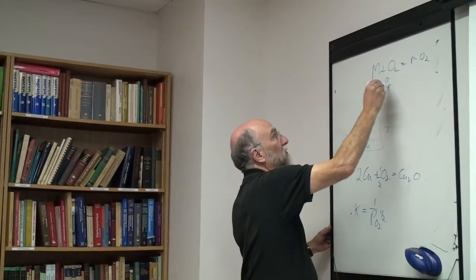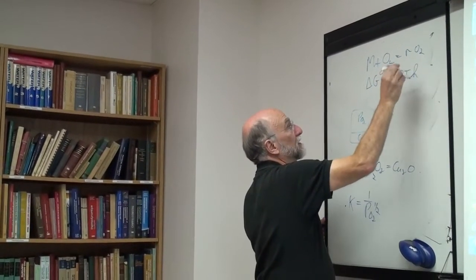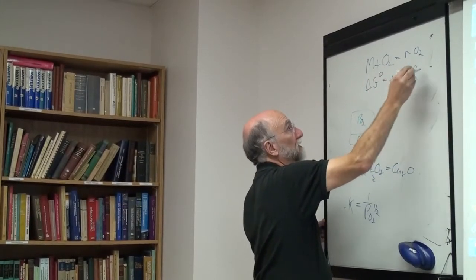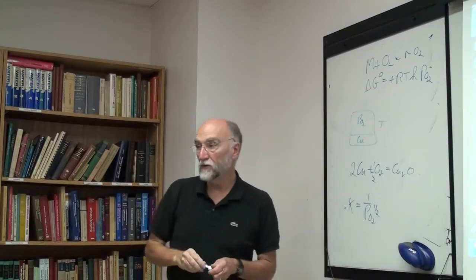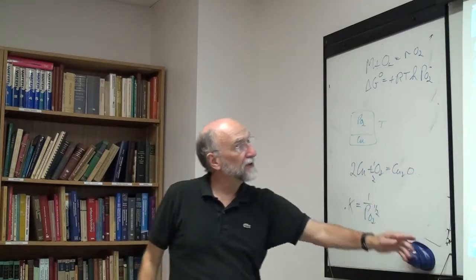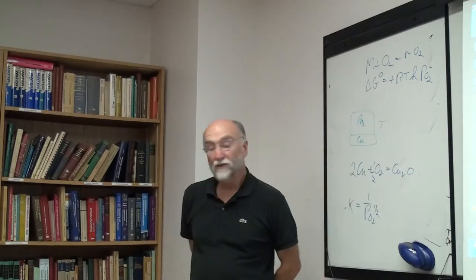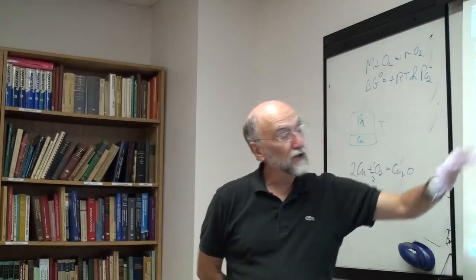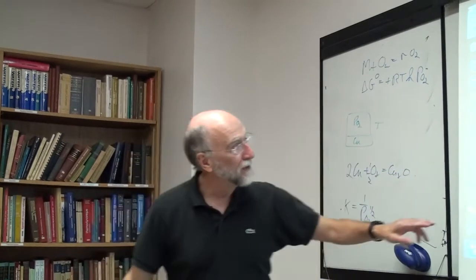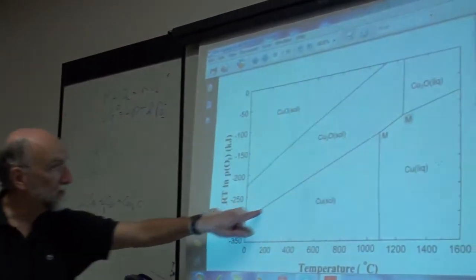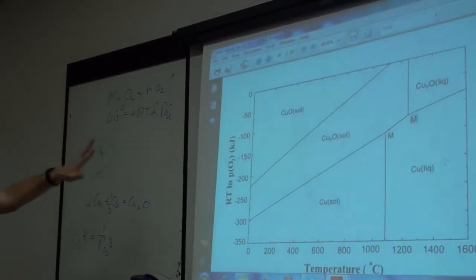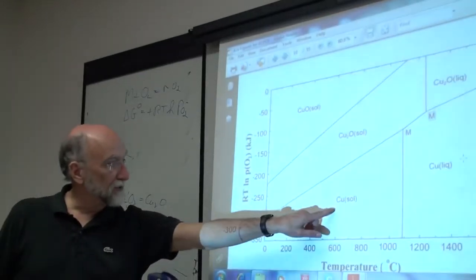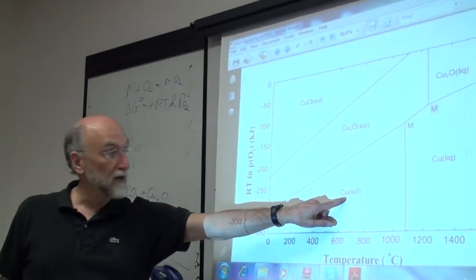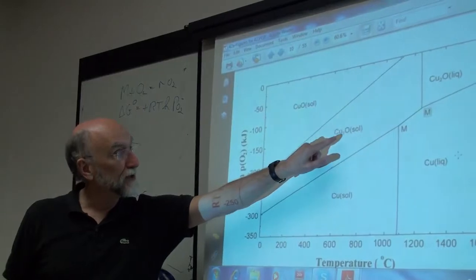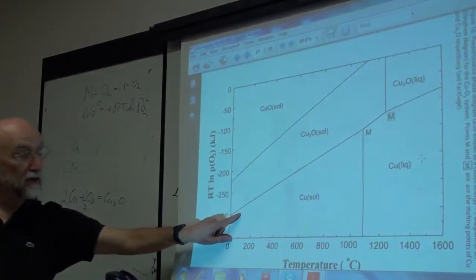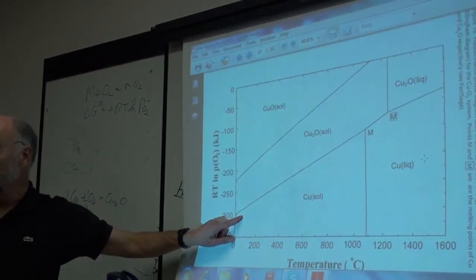Delta G0 is equal to minus RT log 1 over PO2, or equal to plus RT log PO2. So basically, the y-axis here is delta G standard for the reaction. Okay, so I've plotted this here as a phase diagram, an equilibrium diagram. I'm saying this line here is an equilibrium. Let's look at it as a phase diagram. At this temperature and this oxygen pressure, this is the stable phase. At this temperature and this oxygen pressure, this is the stable phase.